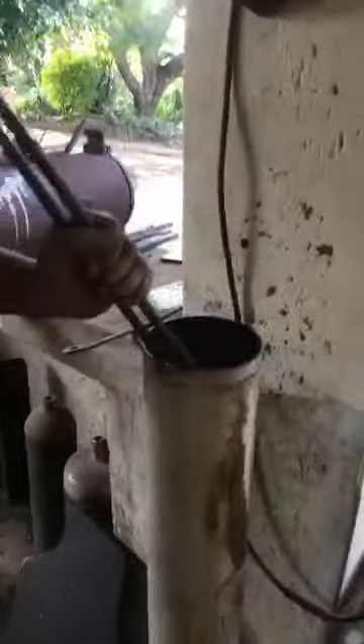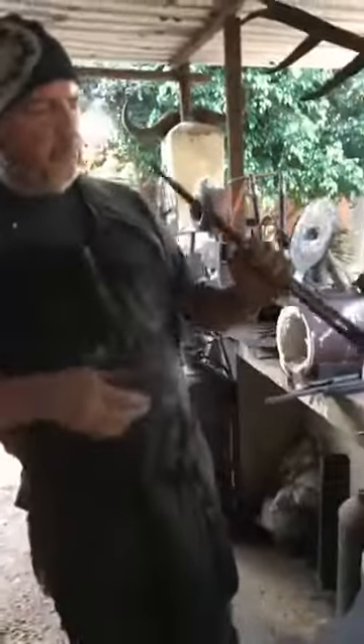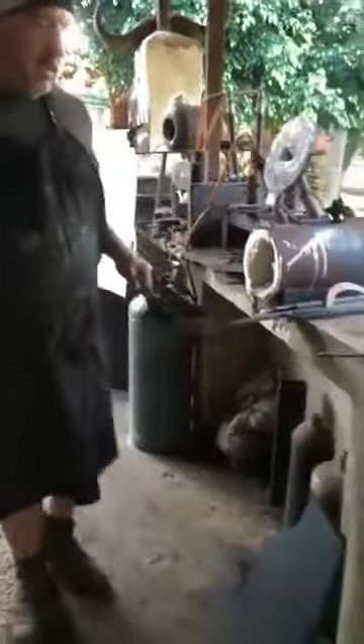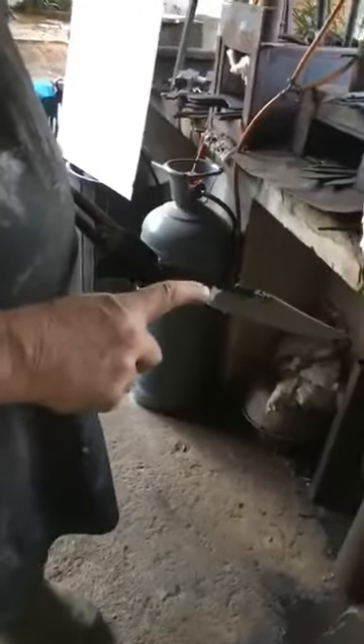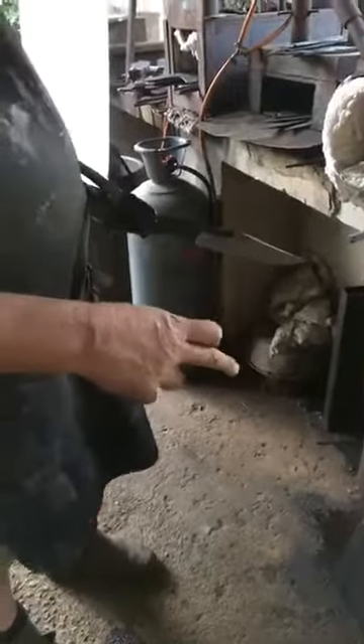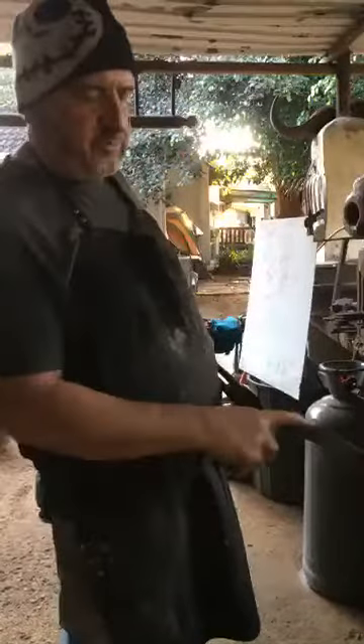So after the second 7 seconds, we take it, and we're going to put it straight in the oil. This is the same oil, by the way. So what I'm doing now is I want to cool down the back. So if you harden your edge, cool down your edge. So harden your edge first 7 seconds, cool down your edge second 7 seconds, then you have to cool down the back. If you don't cool down the back properly, that heat in there is going to temper the edge, and you're going to find yourself with a too soft cutting edge. So you have to cool it down.